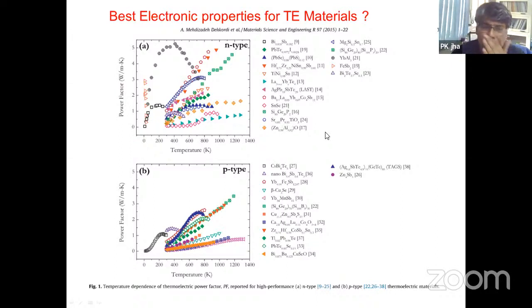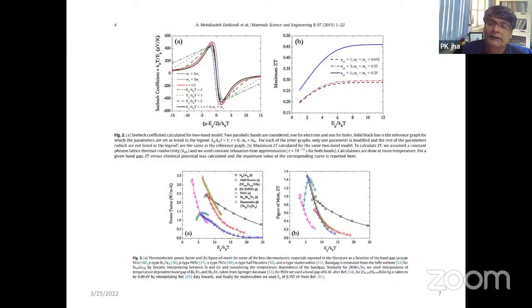So of course, I have considered a few parameters. You can see here that the power factor for most of the materials lies between 0.8 to 2 or so, and the highest value for the power factor is for this particular material, YbAl3. Similarly, this is for the N type. Similarly, for the P type, you can see that in the range of temperature from 300 to 800 Kelvin, most of the values are below 2 watt per meter Kelvin, right? So this is how the important factor related to the power factor is there. Now here, because I was talking about the electronic structure, you can see most importantly what the parameters are in this particular case.